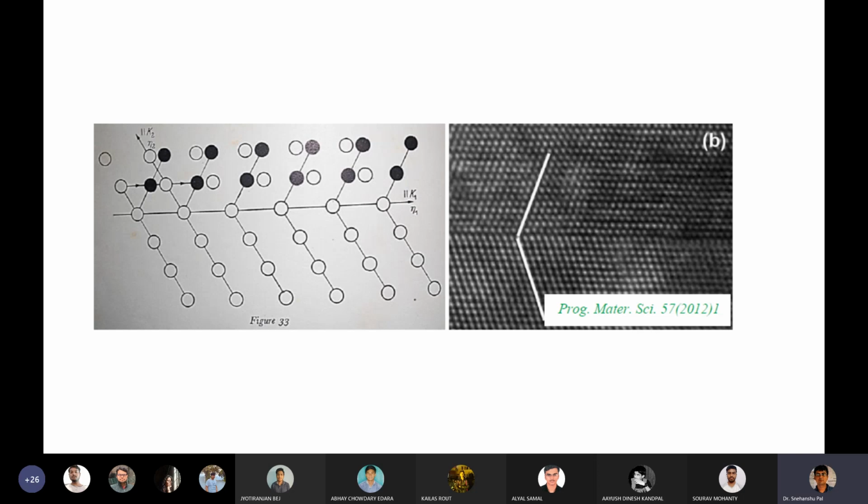Or if you take certain deformation processes at high strain rate, then also you are going to see the twin deformation mechanism. When are we going to see it? When the dislocation glide phenomenon is not so easily operative. You should remember that. Now, if you look at the picture, atoms just above the twin plane move in a coordinated manner to produce shape change. Unlike slip, due to dislocation, where the intermediate location of the dislocation causes deformation. So it is not the same. There are striking differences, so you should remember that and pay attention to it.